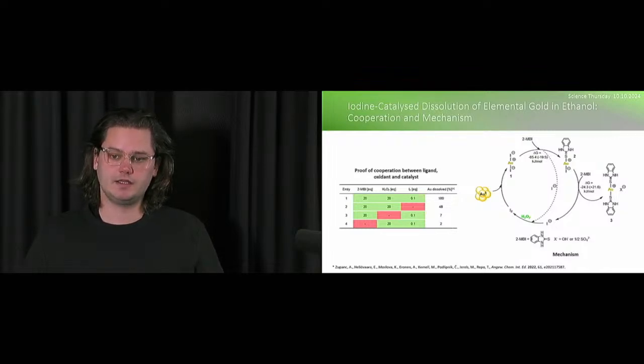catalytic cycle where gold is first dissolved with elemental iodine to form this species 1 on the slide, so gold iodide, and then we chose this organic ligand that was only soluble in ethanol. Of course, this one is insoluble in water, so we could play with different organic ligands, as I said before, just because we have less polar media, organic media. So we chose this 2-mercaptobenzimidazole as a substituting ligand for iodine on the gold